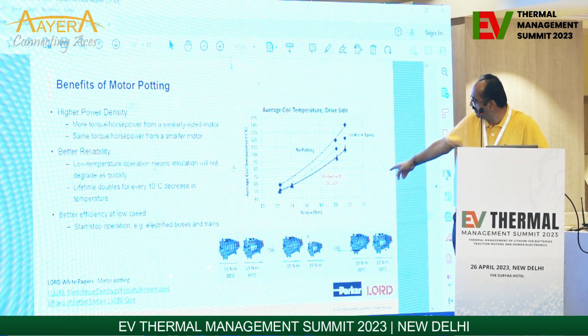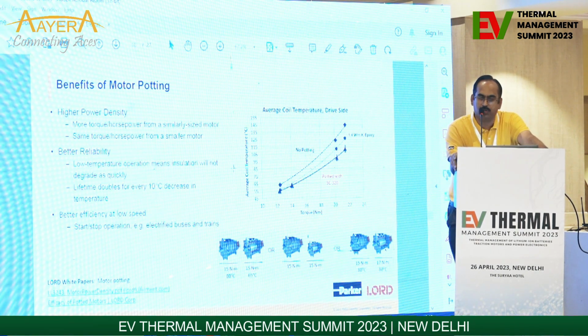So here is the first case, where the same motor with the same output can run at a lower temperature with potting. Instead of 80 degrees, the service temperature is 65. So with potting that is possible. Or the same motor with reduced size but with the same input is possible with potting. Or the third case, the same motor but with higher input can be achieved with potting material. So these are all possibilities with motor potting with Parker Lord materials.